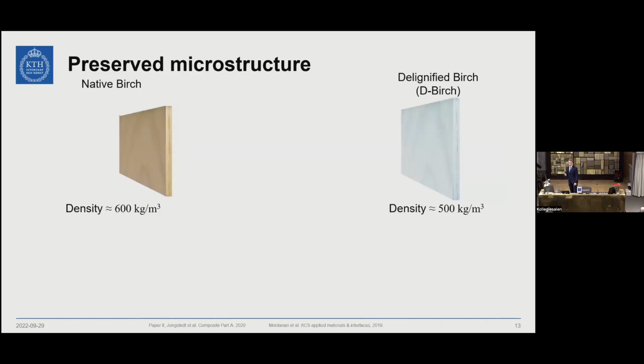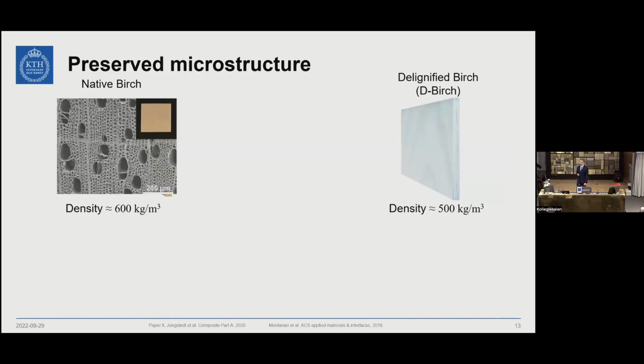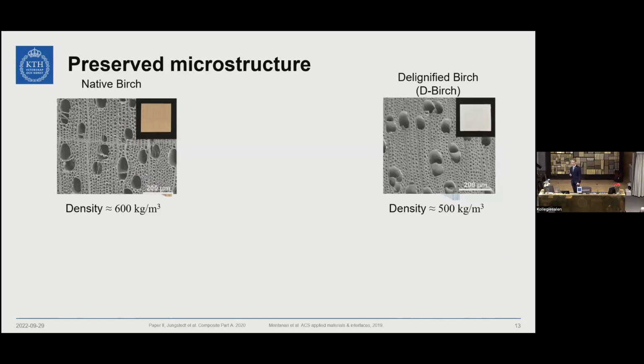So what we do then, we can look at microscopy how these two materials look. So you can see that by doing the delignification, we don't destroy the wood structure; it's still intact. And then we can add PMMA to both of these composites, and then we get these two types of composites: one which is more translucent, one which is more, well, the transparent wood, with the improved optical properties.